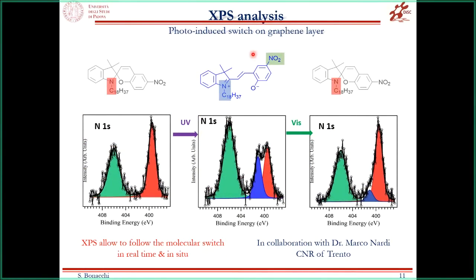And we also perform XPS analysis to prove the tuning of the photoswitchable molecule. From the closed form to the open one, you can clearly see the modification of the binding energy of a nitrogen atom from the closed one to the zwitterionic one, the charged one, and then back again to the closed one. So another proof that we were really able to switch in situ and in real time our photoswitchable molecule on top of the graphene layer.